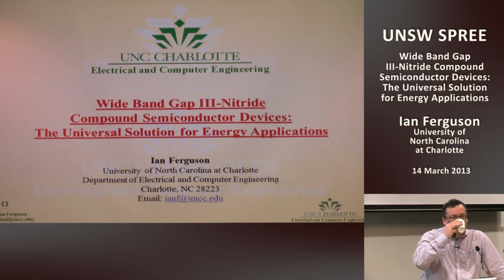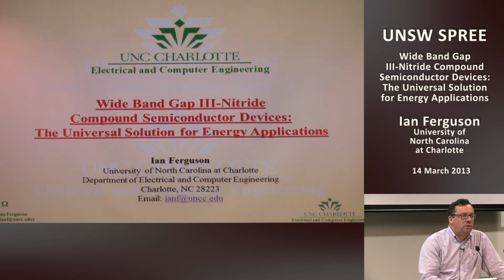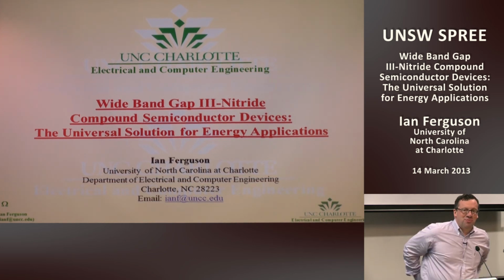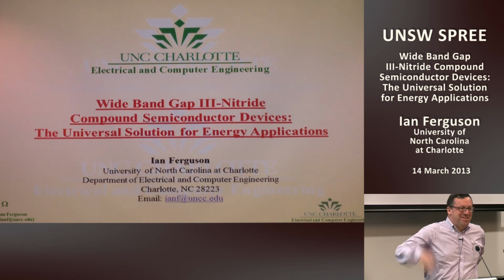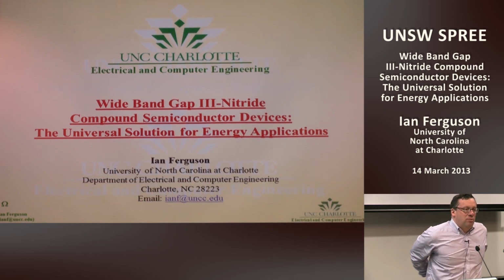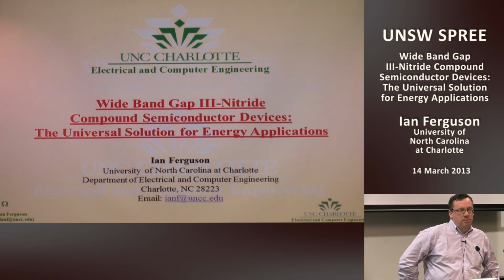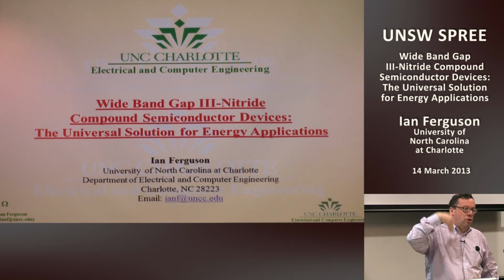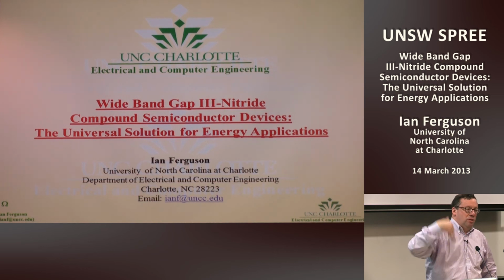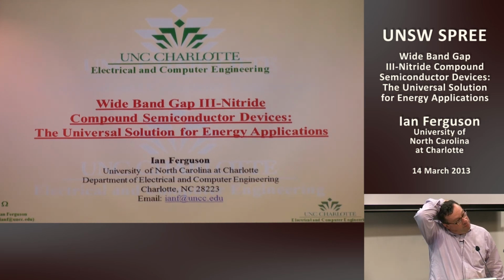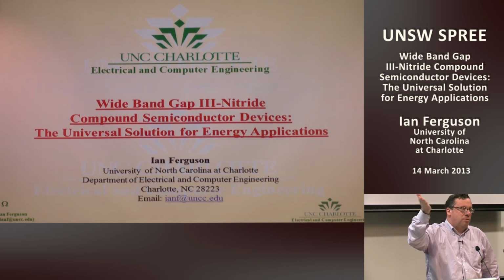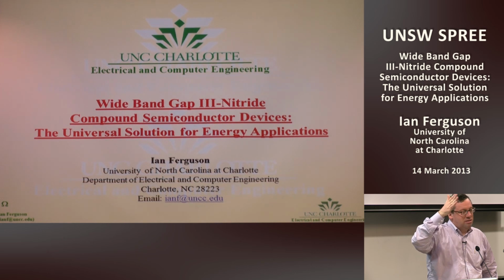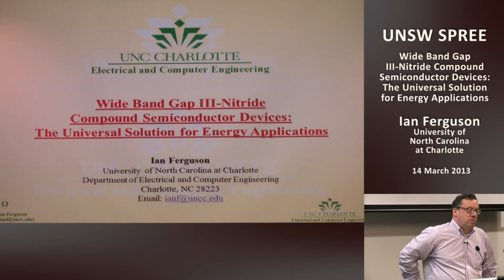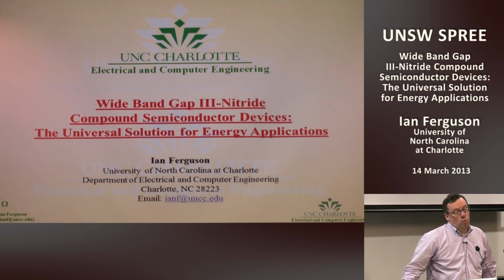I was just wondering what your growth temperatures were and how they varied with your indium concentration. So, your basic gallium nitride grows at about 1050, but there's a whole nucleation process of nucleating amorphous, recrystallizing, then renucleating. For your gallium indium nitrides, you'll typically drop the temperature down to around 700 to 800 degrees centigrade, depending on what type of material you're growing, what composition, what growth rate you want, and what you're doing with the homogeneity of the materials.